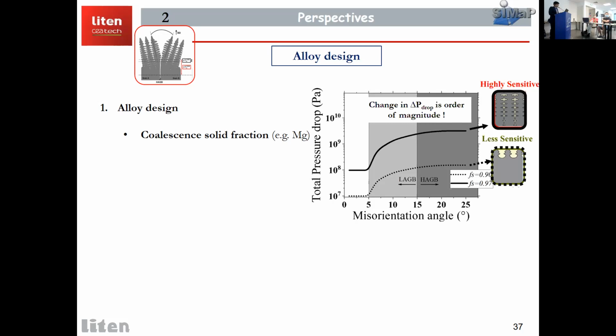And to achieve a low coalescence solid fraction, we can think, okay, we have found in literature that magnesium is an element which can have an effect on coalescence solid fraction. With magnesium addition, we can decrease the coalescence solid fraction.